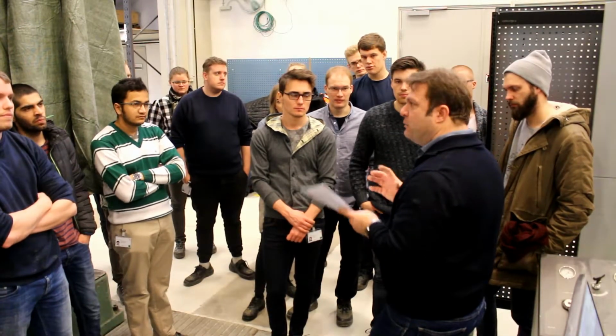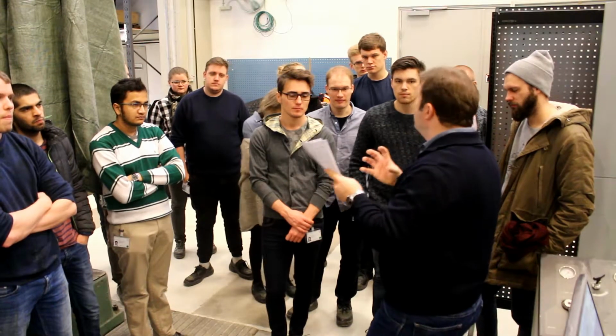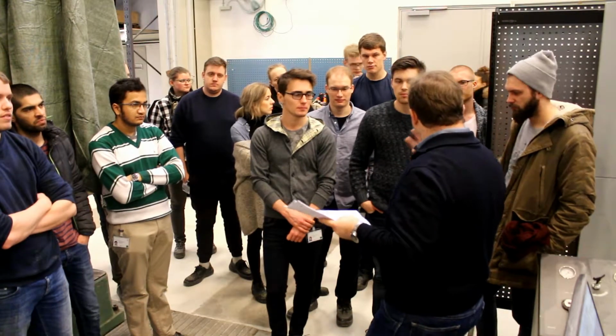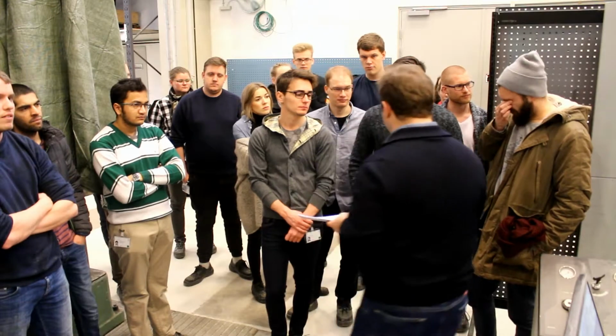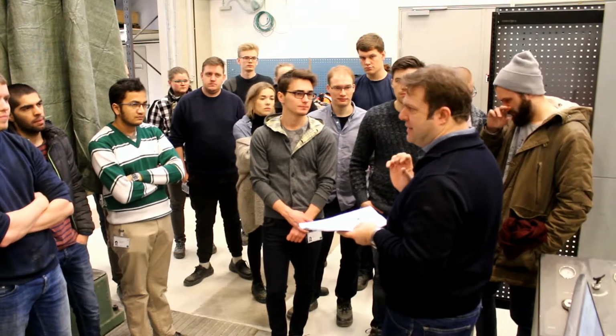Around 1/10. 10%, exactly right. So about 3 megapascal we would expect in direct tension. Yeah? The flexural strength of an unreinforced concrete beam is also 3 megapascal.